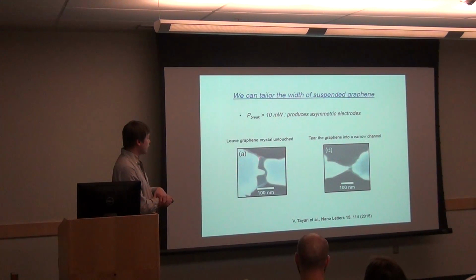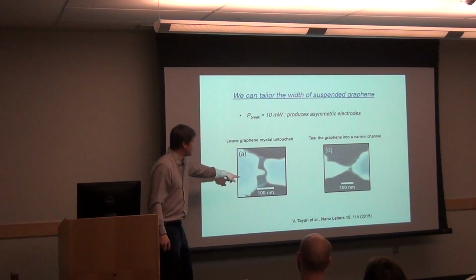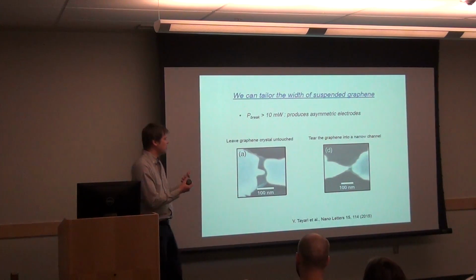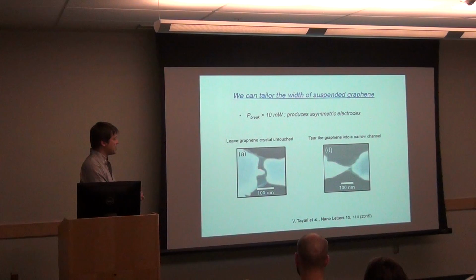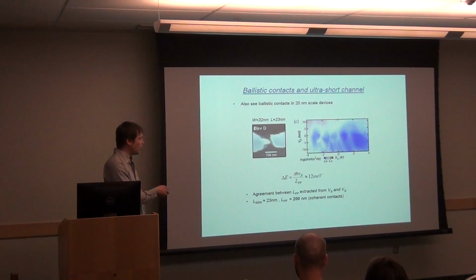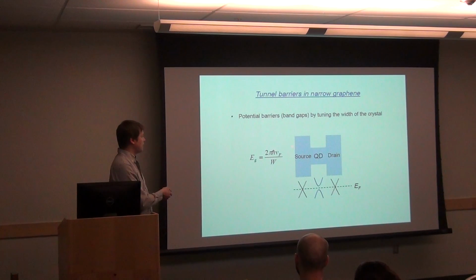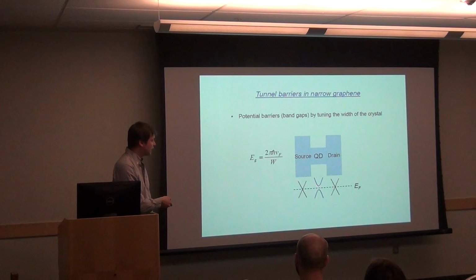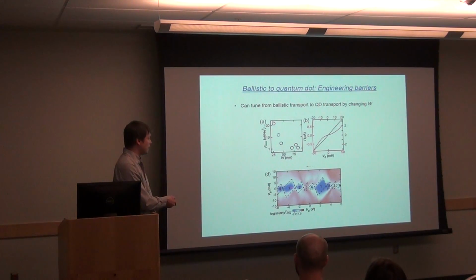We can also tune not only the length of the devices, but the width. It turns out if you use different power, you can create very asymmetric shapes in the electrodes, and this is actually a controlled process. You can think of this as a finger, right? And now you can apply fields to rip the graphene and make narrow channels. When you make narrow channels, you can have open quantum dots. In this case, you see Fabry-Perot interferences. Again, the point is that this device is ballistic, and you also have ballistic contacts, so these interferences are from the contacts. And if you make them narrower, you can also make quantum dots. So the width boundary condition here can open a gap in graphene, and you can see that in transport.